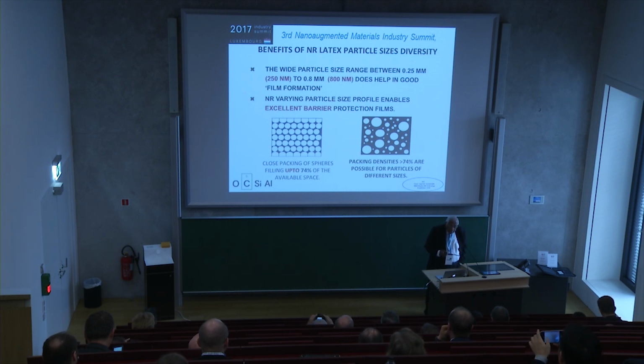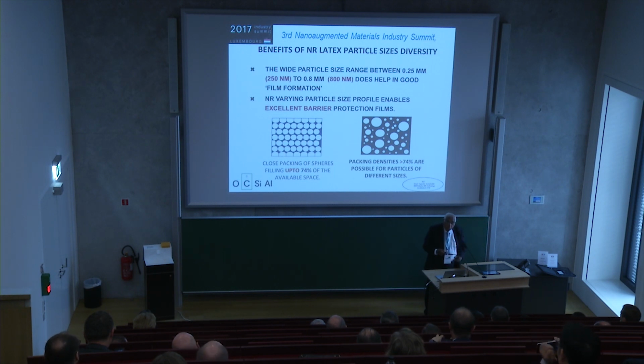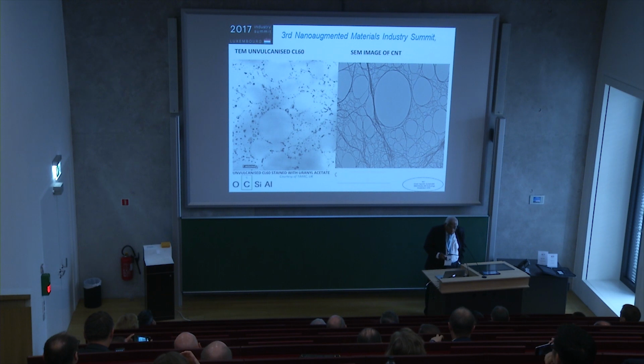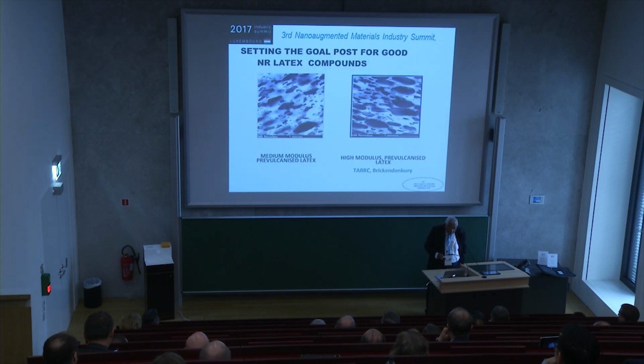The benefit of diversity in particle size, of course, is that we get very good packing, better than spherical packing. So the impermeability characteristics are better because of the better packing of the latex particles as it dries down into film. So here I've got a TEM of unvulcanized natural rubber, and the image provided by OCSiAl of CNT. You see a similarity in a way between the two of them.